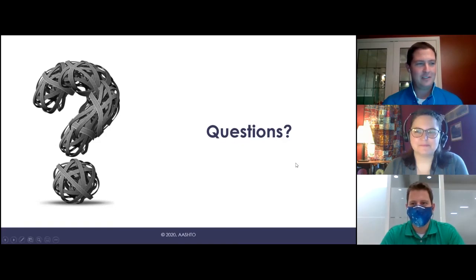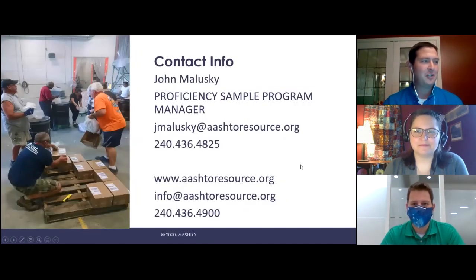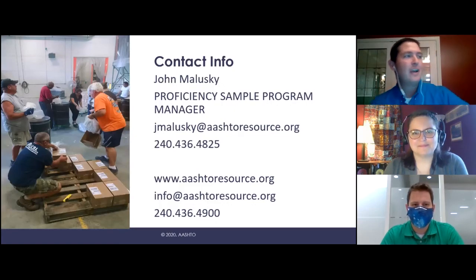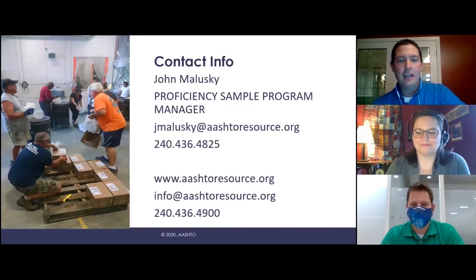I'm kind of jumping ahead, but this picture here on the left is a notorious dump day for a coarse aggregate sample. We load the material into our hoppers and we weigh the material to specific gram amounts in the boxes for the coarse aggregate samples that you guys have. And we had one of our engineering technicians inadvertently put a 3/8 inch drum of material in the 1/2 inch hopper. Fortunately, we caught it during the homogeneity testing, so none of the laboratories received any of those samples, but it forced us to throw out 600 samples.